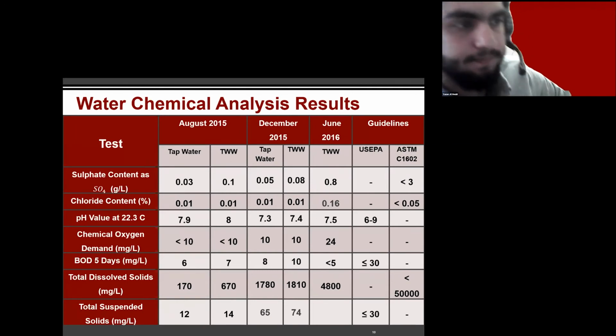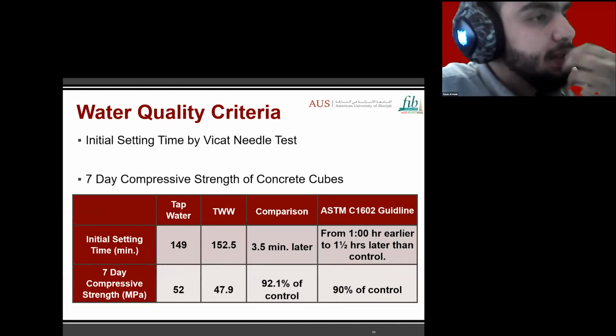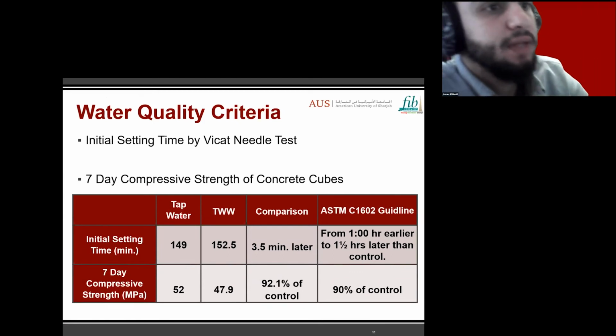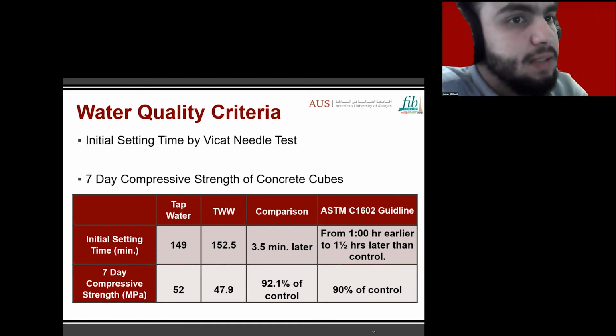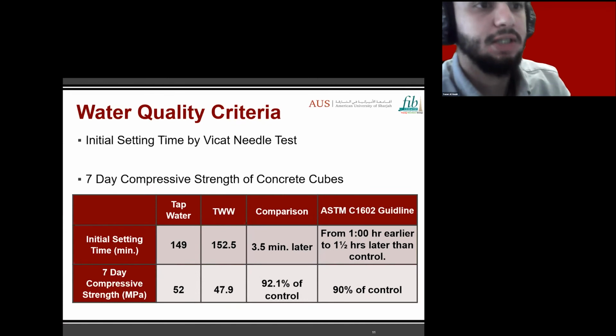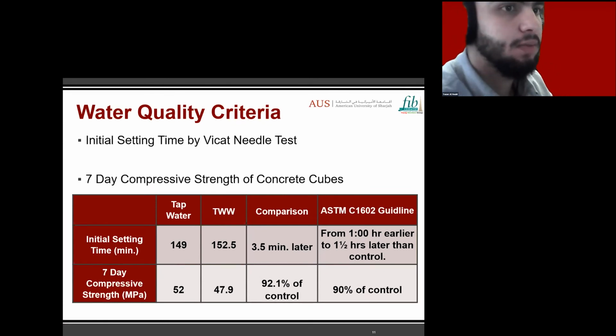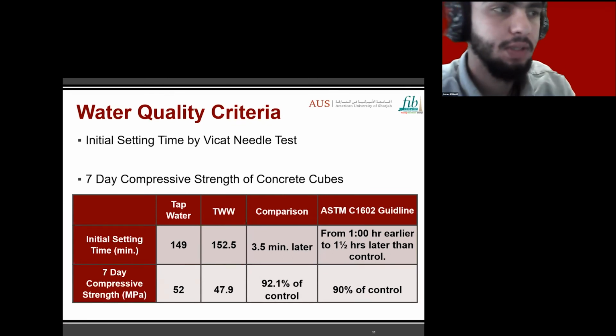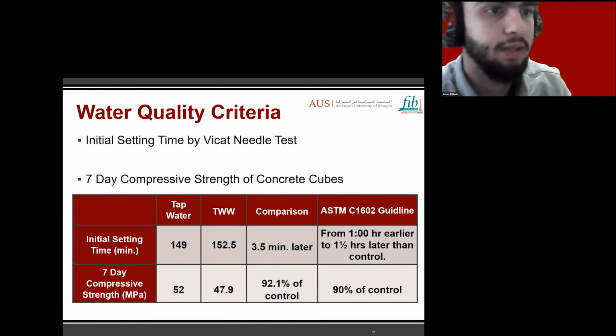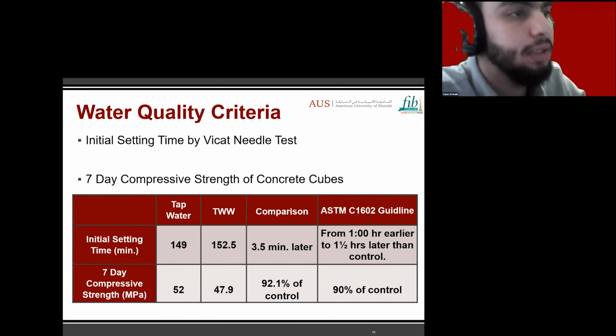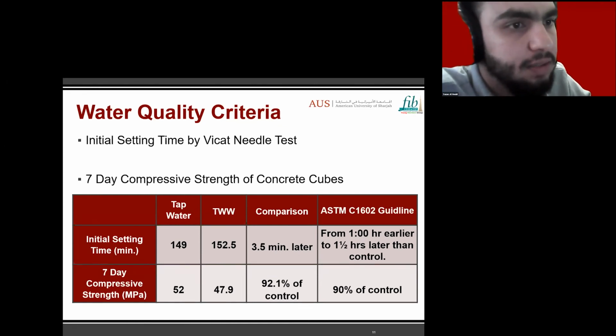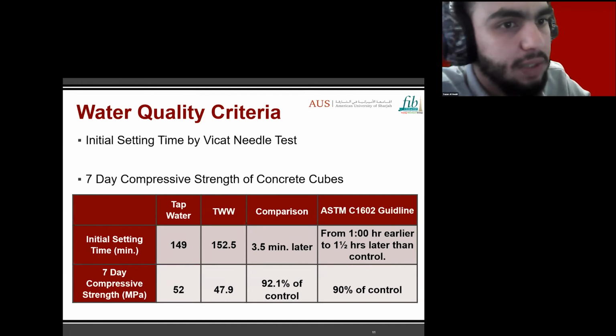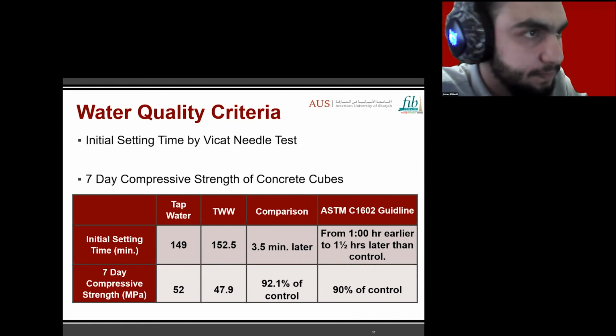A preliminary mix was performed to ensure that the mix design developed meets initial criteria set by the ASTM guidelines for mixing with the treated wastewater. As you can see in this table, the water used was able to meet those criteria, where the initial setting time was only 3.5 minutes later, and the compressive strength was around 92.1% of the control specimen.